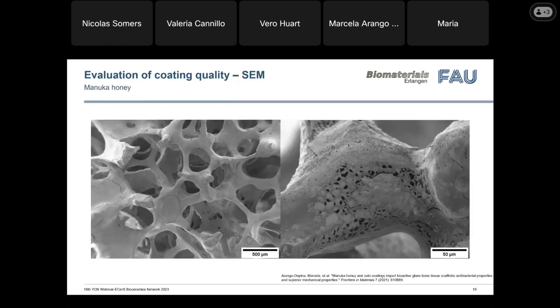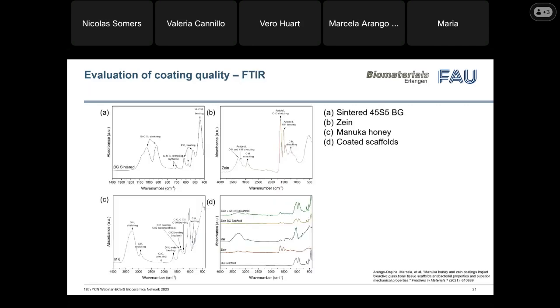Then here we can observe the coating containing Manuka honey. In these SEM pictures, we can see this as the dark spots. This was quite interesting for us because we could really see the difference between having honey or not. So it was easier for us to observe this through SEM. And here we also have another example of a scaffold with honey, but with a higher concentration. So we can even see it at the lowest magnification, which we couldn't when we had a lower amount of honey.